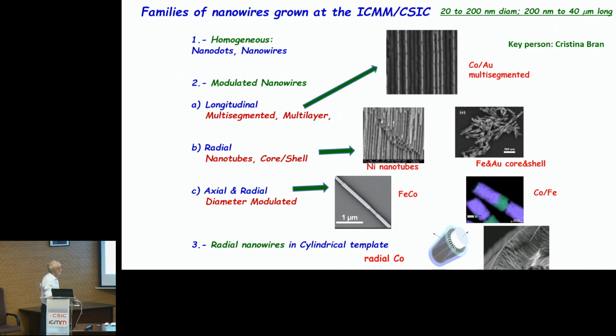In the laboratory, we have prepared, particularly Cristina Bran, she's now in Zaragoza. She has been responsible for the fabrication of many different families of nanowires. For example, nanowires with homogeneous composition and diameter, but also modulated nanowires, where this modulation can be in the longitudinal direction. For example, you see this is a cobalt gold multi-segmented nanowire, or in the radial direction. For example, you see, can be nanotubes or core shell nanowires.